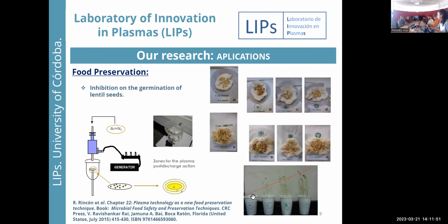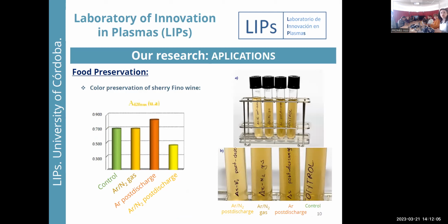These are the lentils that are more affected by the plasma, and then less and less. This result was really promising, so we tried to move forward and also applied the post-discharge to sherry Fino wine, just to see how this plasma could affect the browning of the wine. We treated some samples with argon nitrogen gas only, another sample with only argon post-discharge, and the last one with argon nitrogen post-discharge. After 2 years of storage in a dark environment, we realized that the samples treated with the argon nitrogen post-discharge keep the original color of the sherry Fino wine.